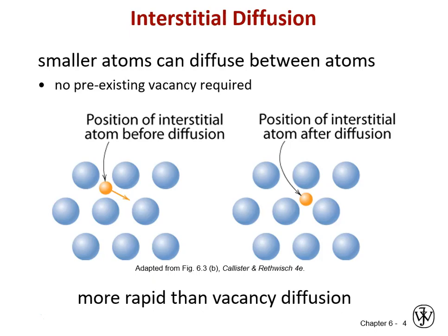These are the 4-fold and 6-fold holes that we discussed in our crystallography discussion. So an interstitial solute that is diffusing can jump to any of the unoccupied interstitial positions around it. So until you get close to filling all of those, which is a rather rare occurrence, there's generally no need to wait for a position to be open. So effectively any position is open.